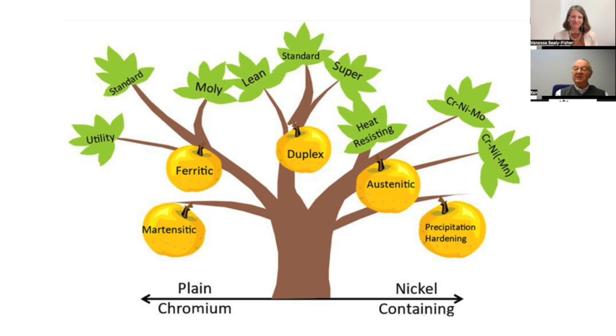The strengths of the duplex material, because they have the high strength, certainly your equipment, your bending equipment, your fabrication, your cutting equipment, wouldn't be able to tackle the same sort of thickness of the duplex grade as maybe you can do with your 304s, 316s. When it comes to machining, you would have to change your machining parameters, because you would probably have to apply greater forces during the machining operation. So one needs to bear that in mind. Another thing is, because of the more complicated metallurgy, the material cannot be stress relieved as you would a structural material. So that needs to be taken into account. And similarly, hot forming needs to be done in somewhat different way.